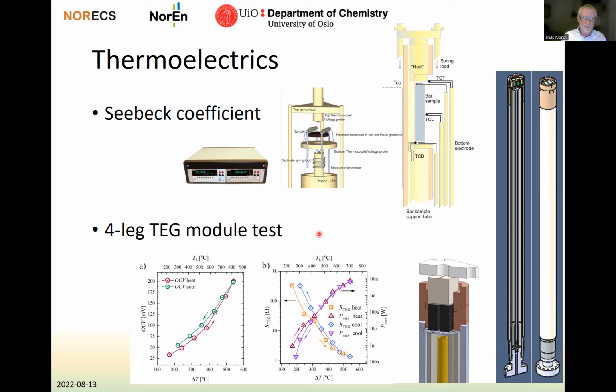We have also recently developed a 4-leg thermoelectric generator module test. The unit, the test module, sits here on top of a support tube in the ProboStat. This support tube is now a closed steel tube that we flush with water so that we keep a temperature between room temperature and 100 degrees here. And on top, we can have a very high temperature from a furnace so that we can create over the legs sitting here, 1, 2, 3, 4 legs here, a temperature gradient of up to 600 degrees. And we can go up to 1,000 degrees here on the outside.